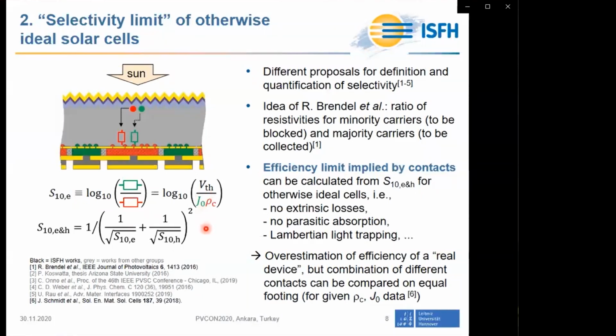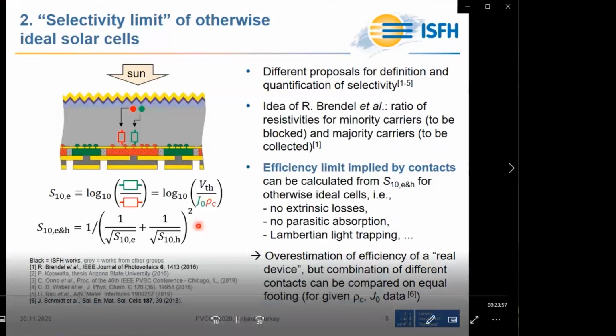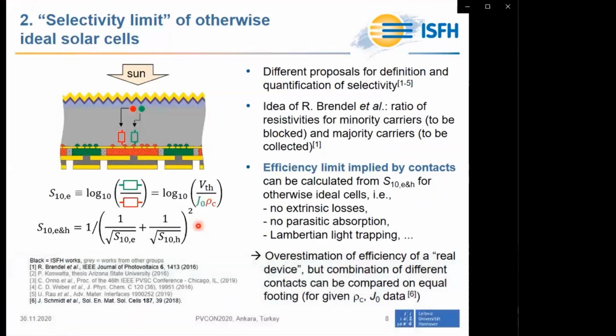As you know, a solar cell has two contacts, and therefore you need to calculate a combined selectivity according to this equation. And as shown by Rolf Brendel et al., this combined selectivity can be correlated to an efficiency limit which is implied exclusively by the contacts. That means the solar cell is considered otherwise as ideal.